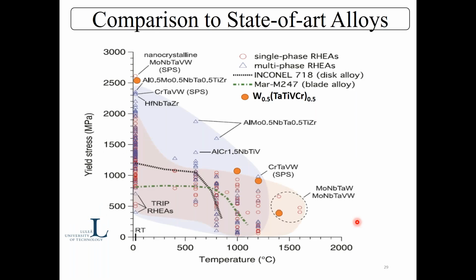So this is a comparison to state-of-the-art alloys, and you can see the existing materials and our high entropy alloy. At room temperature, excellent yield strength. At 1000, better than the existing from the literature. At 1200, also much better, and at 1400. So this way we can design materials, tailor their microstructure, and investigate their high temperature mechanical properties and thermal stability, and we can also use the heat treatment process to tailor the microstructure and the properties.